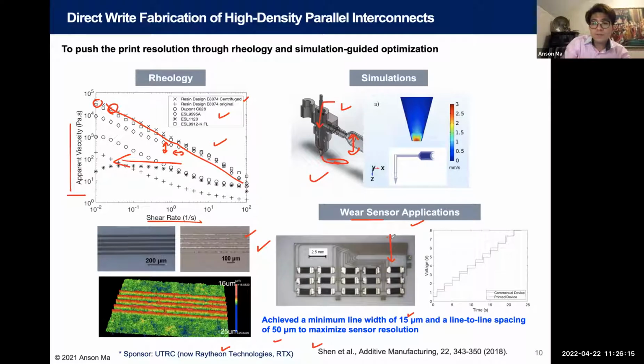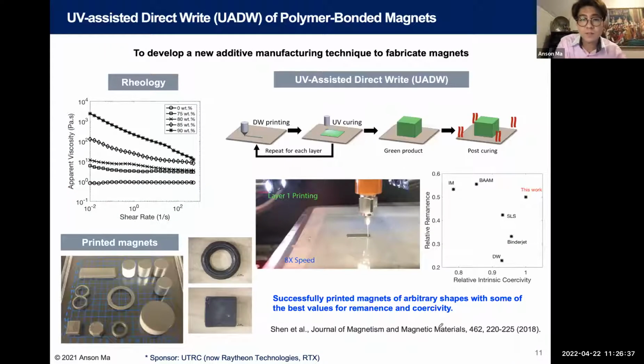Again, it comes from the fact that as the material wears off, you can see a change in the voltage. So the smaller the line spacing that you can do, the higher the sensitivity you have for your wear sensor. So that's why we want to minimize the line width and also the line-to-line spacing for this sensor. And then the trick has to do with the rheology. And again, you're seeing a lot of these rheology plots. Probably you will dream about this tonight.